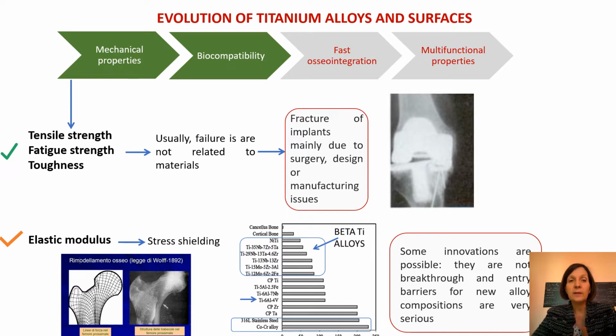So, we had in the history an evolution of titanium alloys and surfaces according to the different requirements. At first, alloys were developed with tensile strength and fatigue strength high enough for the load of an implant, and toughness too. So currently this is a solved issue. Usually failures are not related to materials, and if a fracture occurs, it is due to surgery procedure, to the design or manufacturing issues. As we said, right now there is a problem related to the stress shielding effect. The perspective is to use some beta titanium alloys with a slightly lower elastic modulus with respect to the titanium 6-4, but the difference is not so relevant, so probably this will not be the final solution.